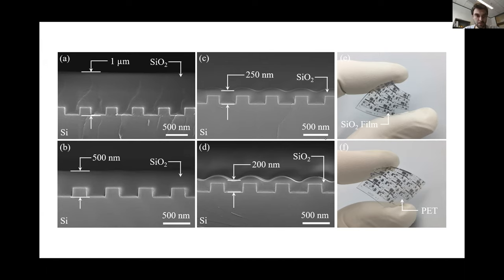And since this is a low temperature process, we're actually able to coat organic materials. For example, on figures E and F, you can see this is a PET sample coated with SiO2. So in the past, it was impossible because SiO2 deposition requires really large temperatures, at least 400 C, to my best knowledge. You can use plasmas, but plasmas damage the surface, so there are trade-offs. And this is just the room temperature deposition of high quality SiO2. In addition, I'd like to add that you can use it for planarization, as you can see from figures A and B.